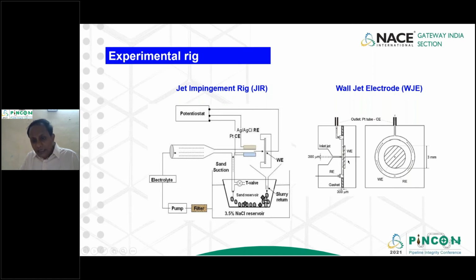Similarly, I kept my NAB, nickel aluminum bronze, surface here. I had the reference electrode here, the counter electrode over here, and there was a gap of 300 micron. The nozzle will go and hit it. This is how I was running both my flow corrosion and erosion corrosion experiments.